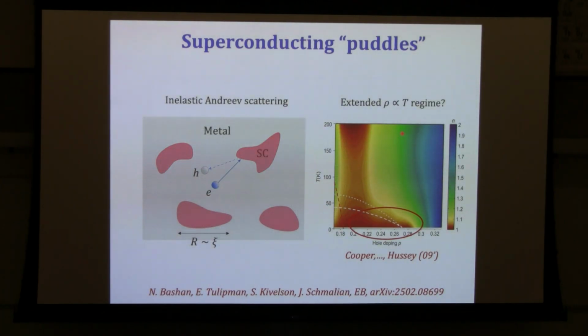Okay, so what we're going to propose, indeed, is that even when you apply these large magnetic fields in the foot to suppress superconductivity, superconductivity is actually not destroyed everywhere. There are these little patches. We're guessing that these patches are just a few nanometers across. So we're imagining a situation where we have a metallic environment and these little superconducting puddles that survive, and these puddles would scatter incoming electrons. This is actually an Andreev scattering. So an incoming electron can get reflected as a hole, and we want to study the possibility that this is actually the source of this anomalous low energy scattering rate that's giving rise to the foot.